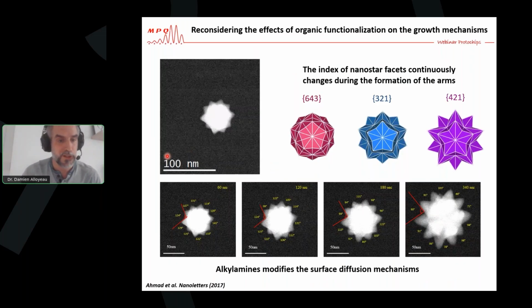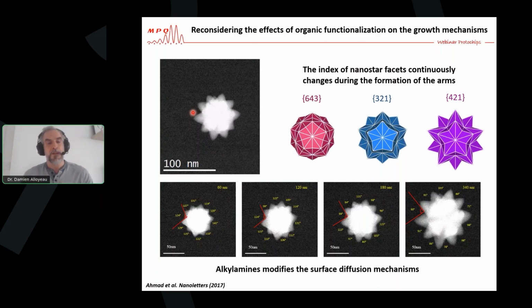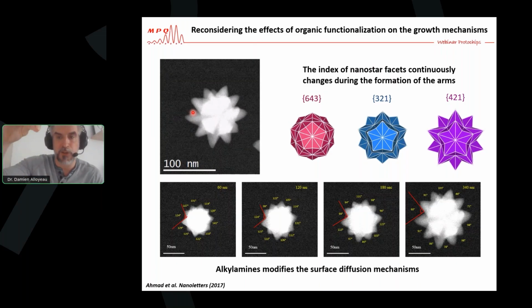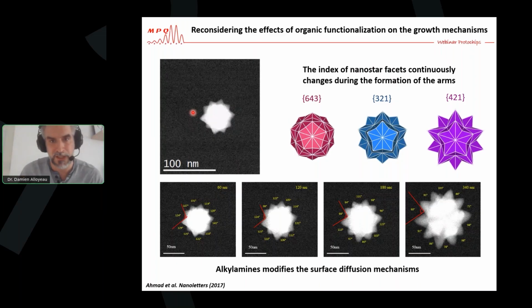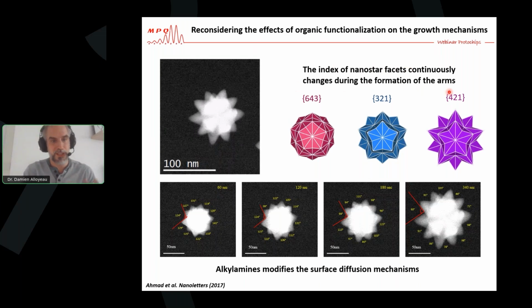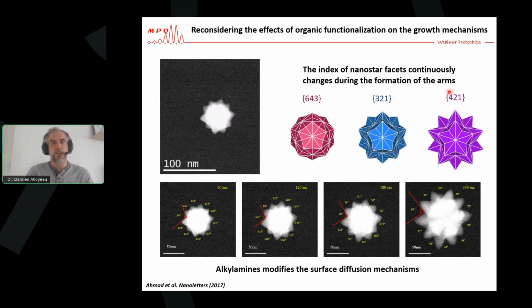And when you now observe the growth process on this video, you see that in fact we never see those truncated arms. The growth process goes as if you were pulling outwards on the 20 arms of the nanostars. And this implies that the index of the nanostar facets continuously changes during the formation of the nanostars. So you see, this type of in situ experiment makes us realize that we have to reconsider the effect of organic functionalization on the growth mechanisms. It does not stabilize a given facet. These alkylamine molecules modify the surface diffusion mechanisms.